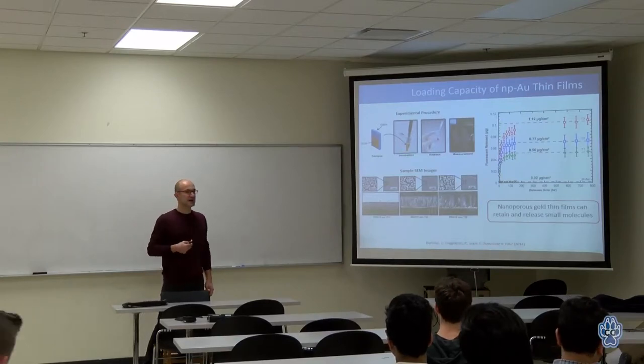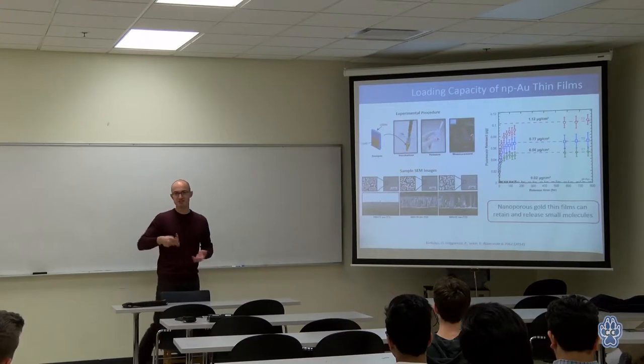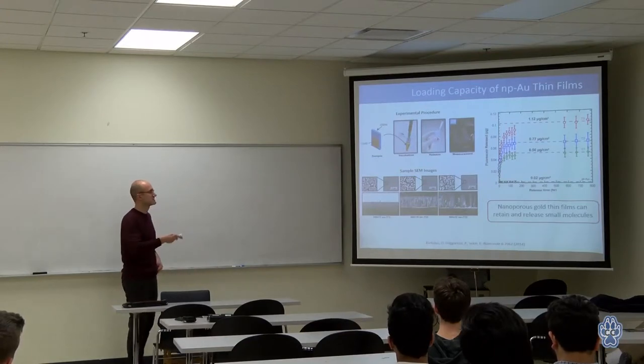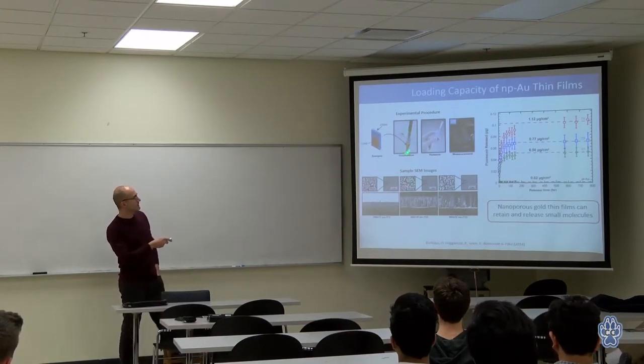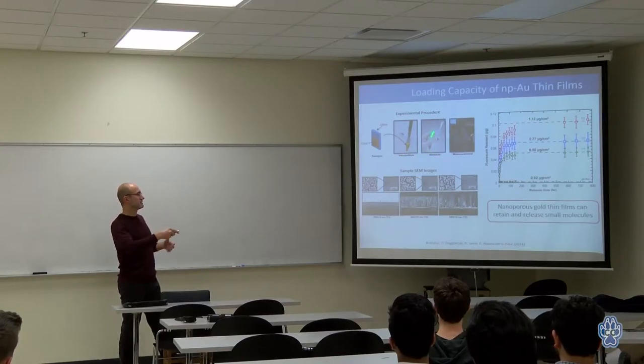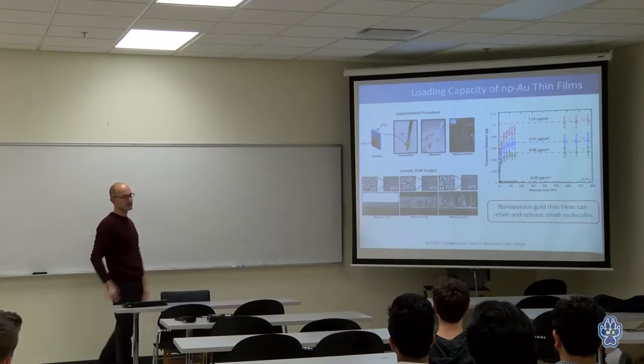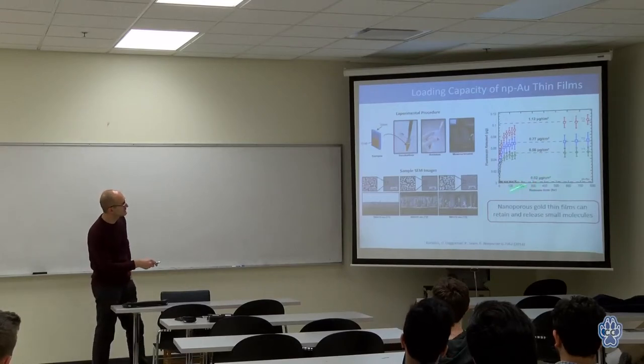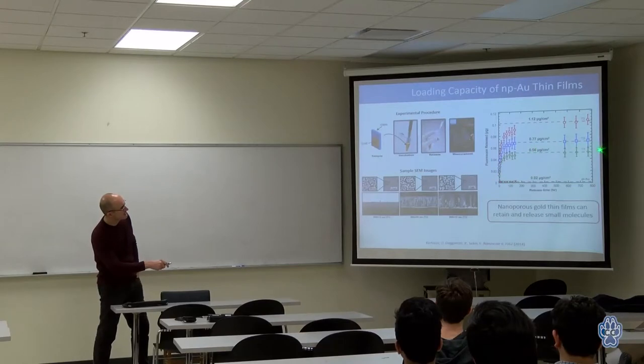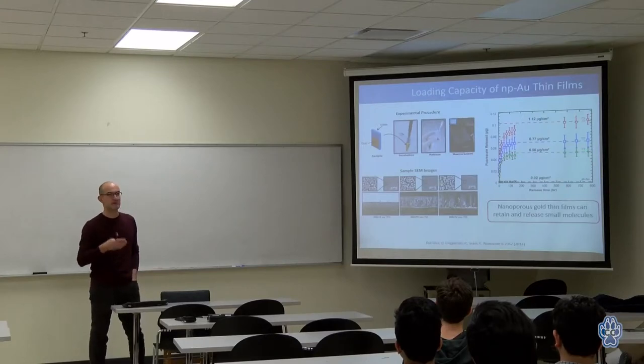Fluorescent, because you can now keep track of them very easily by just looking at their fluorescence, how much is actually coming out. So you incubate them in a fluorescent solution, wash them, and then basically put them in water and look at over time how they come out. What you see here is different thicknesses of these porous films, and over time the fluorescein is released and eventually depletes, and you determine the loading capacity, how much fluorescein was loaded into these surfaces.